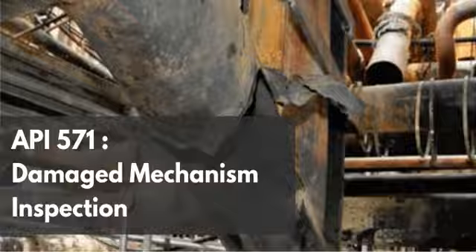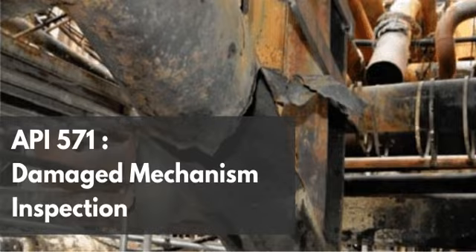Catalytic reformers, cokers, ethylene pyrolysis furnaces, and steam reformers, these are not your standard low-temperature boilers. Not at all. These are the absolute workhorses of high-temperature, aggressive chemistry. They operate at the extreme upper limits of standard metallurgy, often running well over the 1100-degree Fahrenheit threshold as their normal everyday baseline. And what is flowing through them? Pure, concentrated hydrocarbons. They're literally swimming in the exact high-carbon gases that drive the carburization kinetics. Just massive volumes of it.